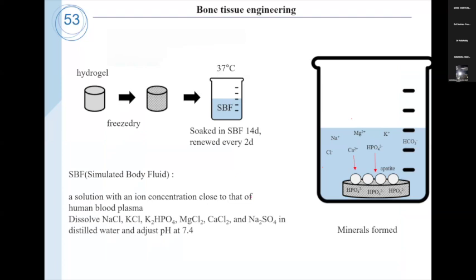So how do we perform the biomineralization? In general, we prepare the simulated body fluid. It is a solution with ion concentration close to that of human blood plasma. So we use various types of salts like sodium chloride, potassium chloride, phosphates, magnesium chloride, calcium chloride, and sodium sulfate. We adjust the pH to 7.4.